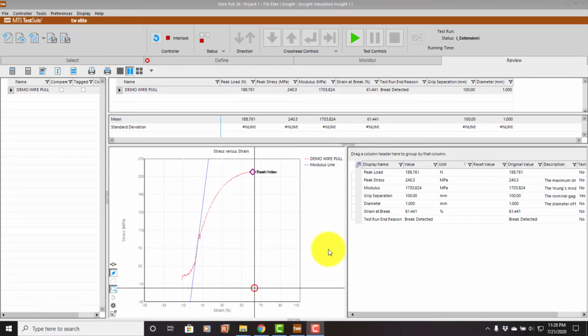Here's that curve again, and what I wanted to show you was that as you pull the wire through the die and you go down to 0.9 millimeter, 0.8 millimeter, this curve is going to get a lot taller. That is, the peak stress is going to rise, but it's going to become more brittle. You won't see this 61% strain. You'll see the strain very quickly drop under 10%. So the curves will get taller and much narrower, indicating a brittle material. And then the annealed samples will all come back and look almost identical to this first sawtooth.